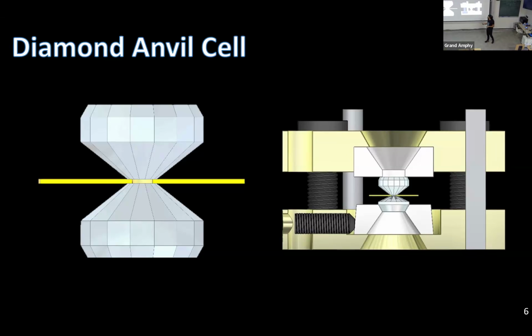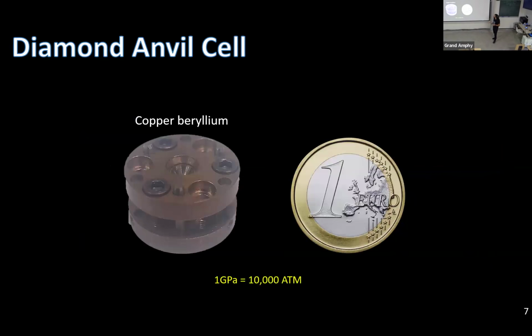Diamond anvil cells have been used a lot. There are many types of diamond anvil cells. Our diamond anvil cell is a pretty unique one. It's a miniature diamond anvil cell, with a diameter around that of a €1 coin, so pretty small. It's made out of copper beryllium, which is a strong material, but also enables us to cool down our samples. We need good thermal conductivity so we can measure our thin films inside our cryogenic measurement.